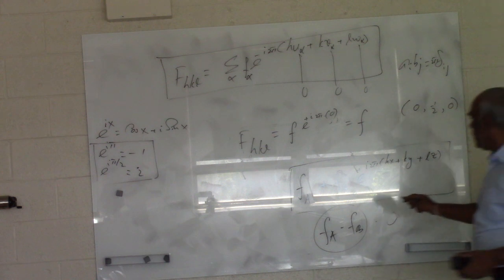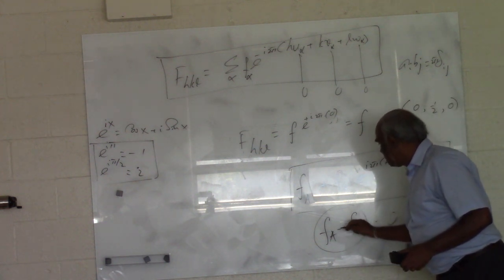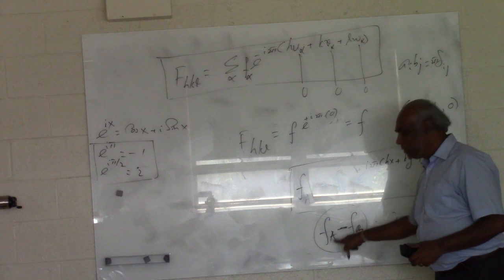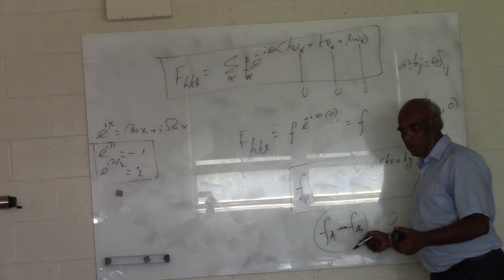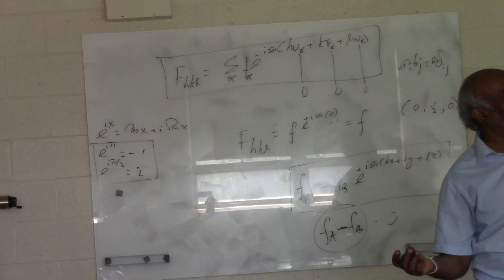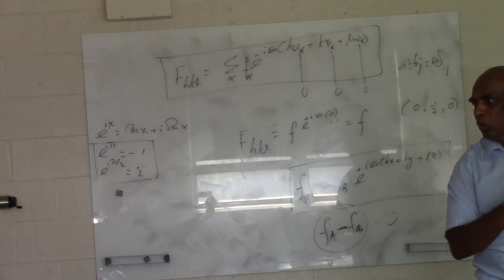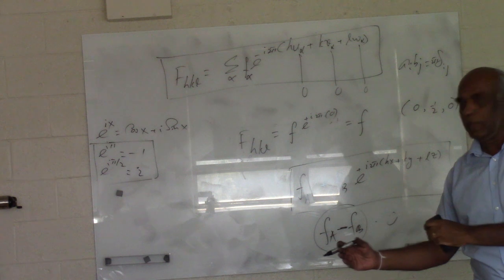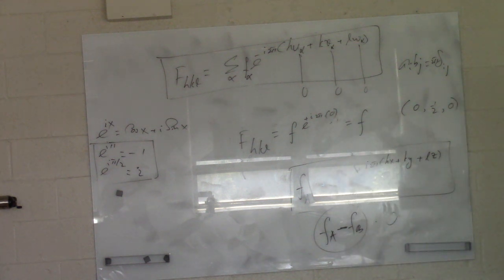You can see now if we have something like this, if they are equal, this becomes 0, right? If they are not equal, it is non-zero. If you take potassium chloride, it is non-zero if all indices are even. We know for FCC, you need to have either all even or all odd, right? So here, for all the even indices, you have these peaks.